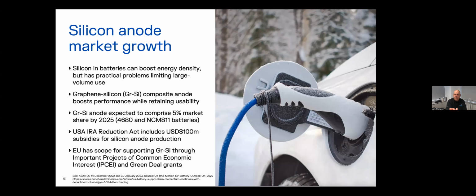So our primary particle does about 1,800 milliamp hours per gram of energy density, which is about 5 times higher than graphite alone. But the customers don't need it that high, and it has other repercussions around longevity. So you want to balance that and put in as much as you need to boost performance, while retaining the length of cycle life and other things you need.